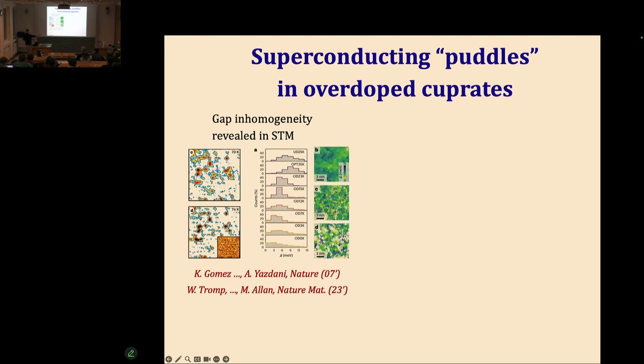And this is a similar plot from M. Allan's group. These are samples with different doping, and the color shows the magnitude of the gap. This sample is actually not superconducting, but still there's a lot of local superconducting-like gaps. Now, there's a lot of other experimental evidence that in this overdoped regime, where linear T resistivity is observed, you don't suppress superconductivity, the ground state is a superconductor, but the superconductor is very inhomogeneous. So it's not that the entire sample has a uniform superfluid density and constant gap. There are actually regions that are superconducting that below TC become phase coherent globally.